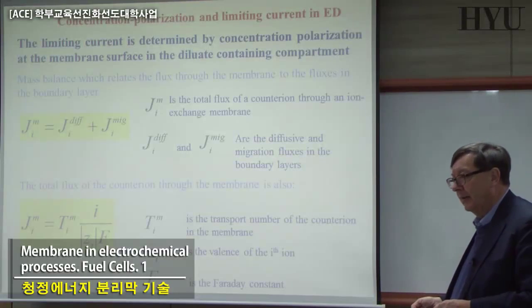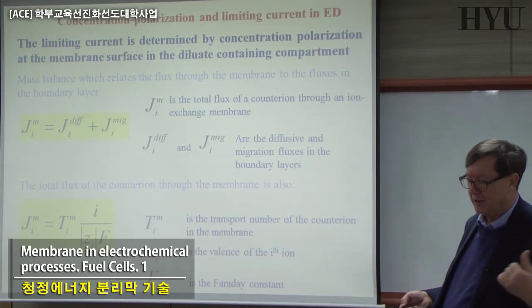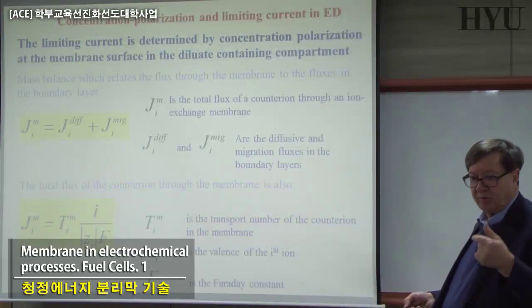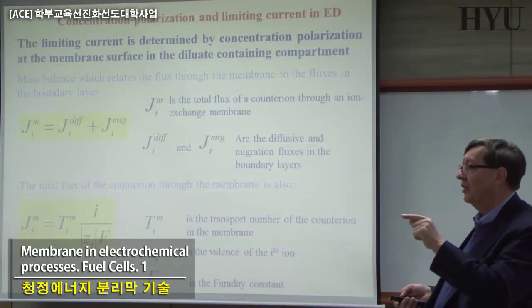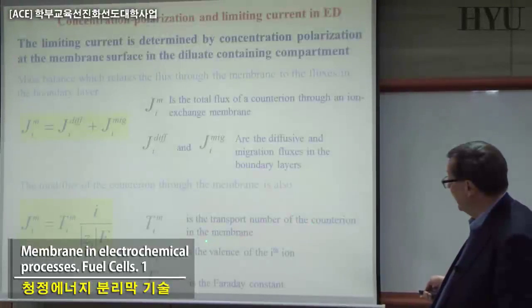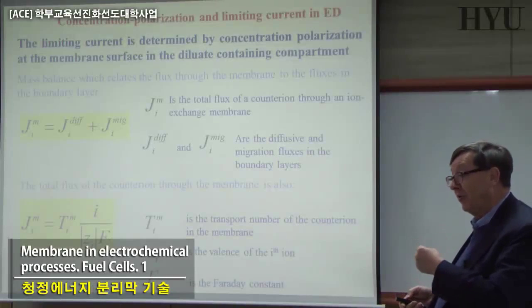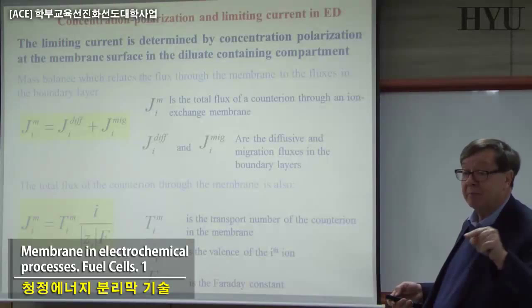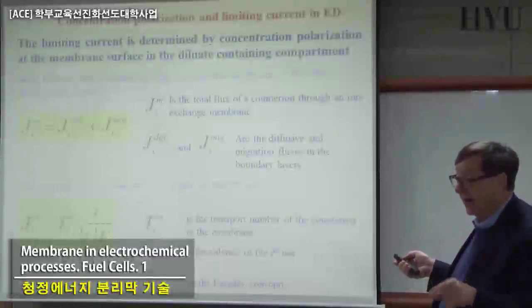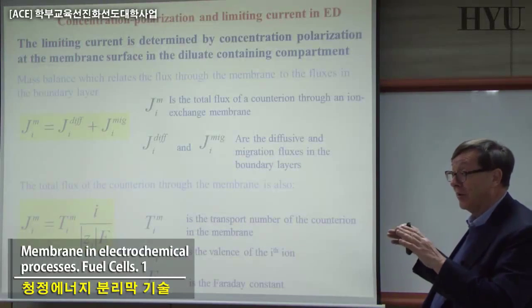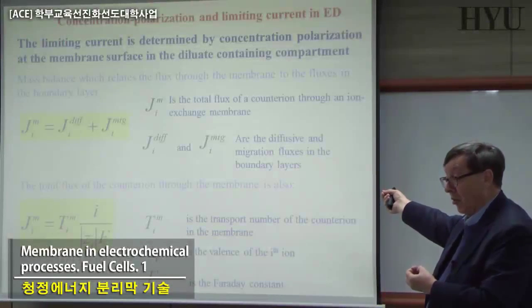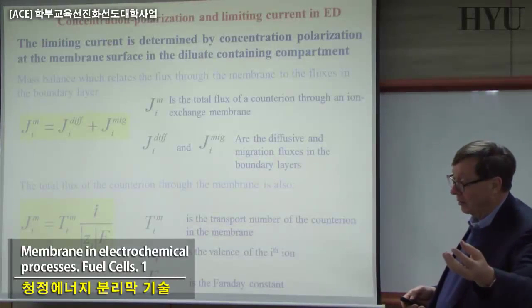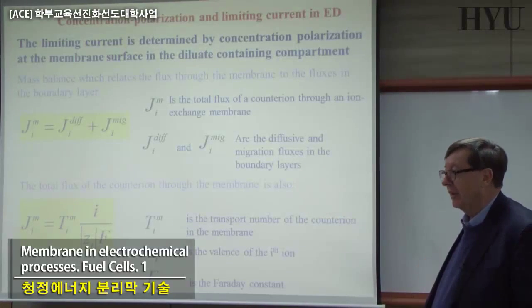And you remember that we defined, I think we spoke sometime, the Donnan exclusion phenomenon. The Donnan exclusion phenomenon is telling you that the concentration of the co-ions is excluded. We define counter ions in the membranes as the ions having a charge different from the fixed one, and co-ions are the ions having the same charge as the fixed one. Now, the counter ions are the ones that avoid violating electroneutrality. If you have one ion with a positive charge, one with a negative charge, and the fixed one is negative, the negative charge cannot enter because there is not another negative that can go out without breaking the chain. If a positive one is entering, another one is moving out, and the electroneutrality is always respected.